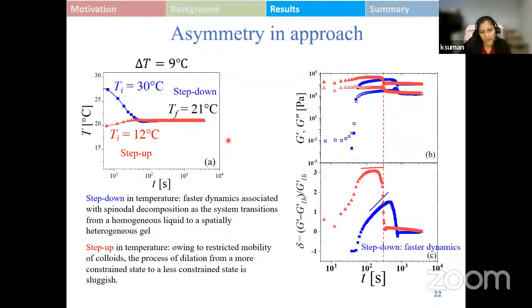For example, in the left figure shown over here, if we take the final temperature to be 21 degrees and try to achieve it from 30 degrees and 12 degrees, how does the dynamics differ in both cases? As we know, 30 degrees is the liquid-like state for this sample, whereas 12 degrees is an arrested state for the sample. As we transition the sample from 30 to 21, giving a step down, and from 12 to 21, a step up in temperature, the following evolution is shown in the rightmost curve over here.